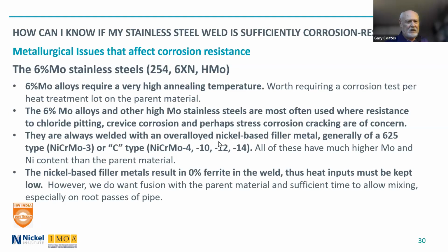However, sometimes there's a little problem with thinking about them. The 6% moly alloys are stainless steels, but they're being welded with a nickel-based filler metal. They have 0% ferrite in the weld, thus very sensitive to hot cracking. Thus, you have to keep the heat inputs down low. These are micro cracks that may not be obvious to the welder while he's welding it. They may only open up 24 hours after he's welded it.